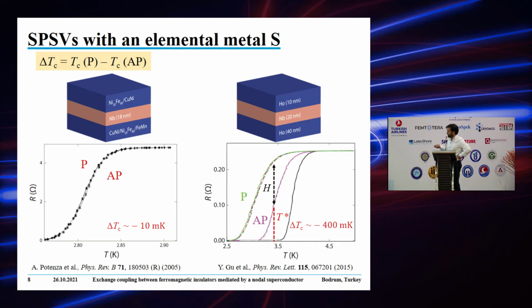Because if you do this, you can switch from one state to the other, so from one curve to the other, and knowing the slope of the curve at this point, you can work out the corresponding delta Tc. So if you do some sweeps on the superconducting transition, and you see a difference between the parallel and antiparallel states, or some features in magnetoresistance, then you can work out the corresponding delta Tc and which state is favored, so which one has higher Tc. I pointed out here that in this case, if you sweep between these two states, you can see that the antiparallel one has lower resistance than the parallel one, and in fact the parallel one has lower Tc than the antiparallel one. So in the magnetoresistance feature, high resistance means low Tc, low resistance means high Tc, and this will hold in all the slides to come.